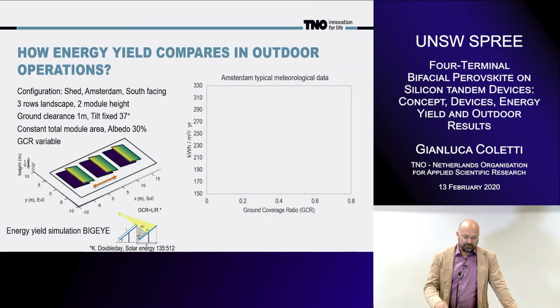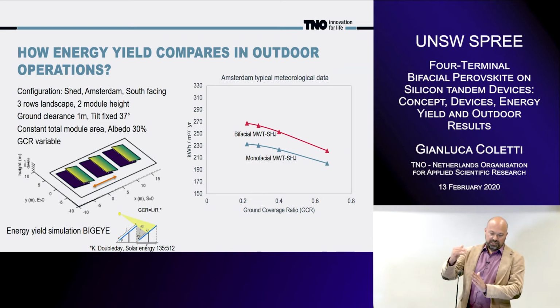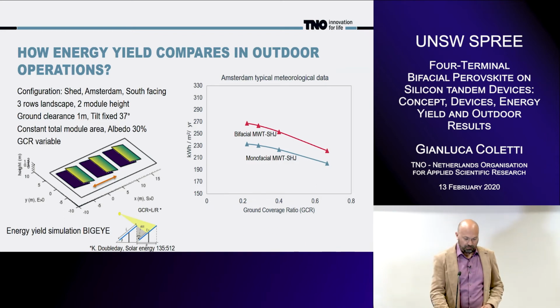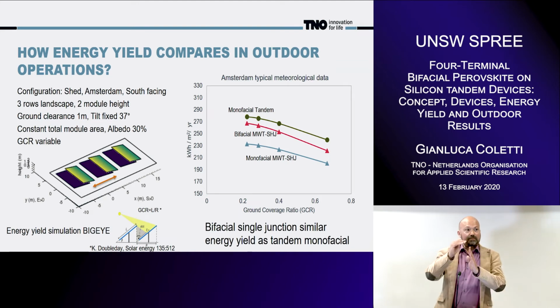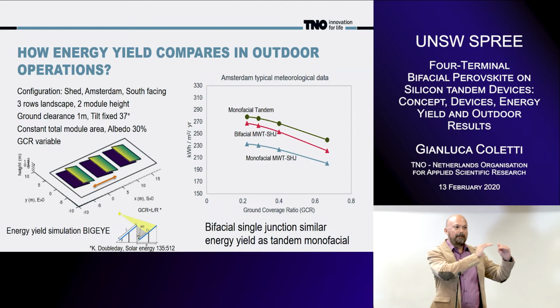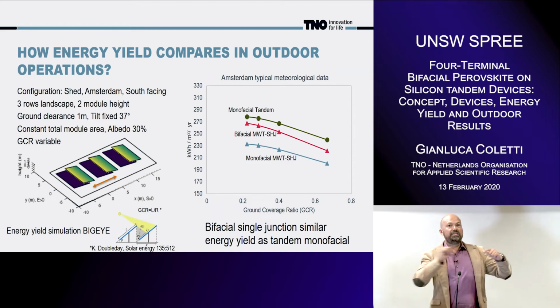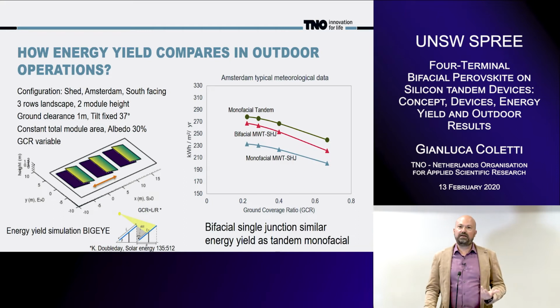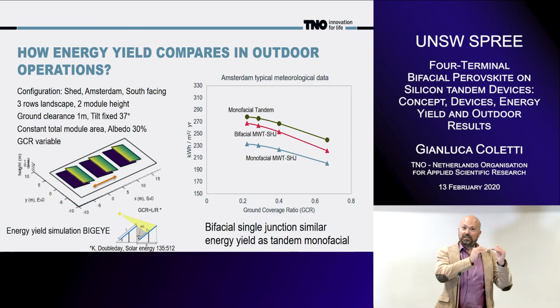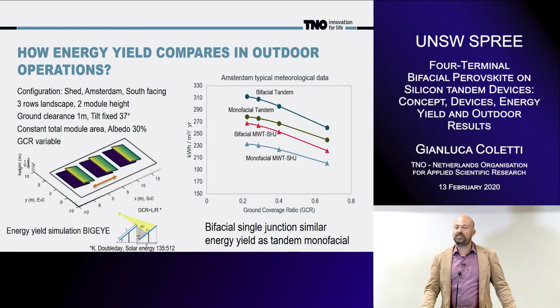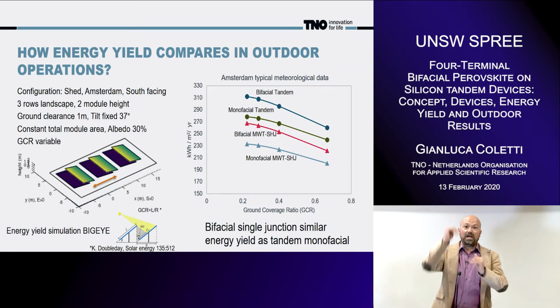So those are the results for typical Amsterdam data in 1 year. The monofacial single junction MWT produced this amount of energy, and the bifacial we see as something like 20% more. The monofacial tandem is a little bit higher, and why is it a little bit higher, despite before we saw it has similar efficiency? The reason is that perovskite has a better response in terms of temperature coefficient and sensitivity at low light. That's why in the energy you see that effect larger than only in standard test conditions. And then the last one is the bifacial tandem, that gives way much more energy.